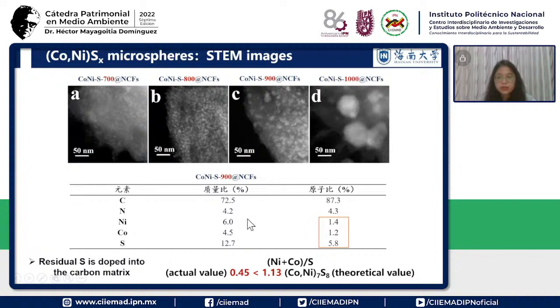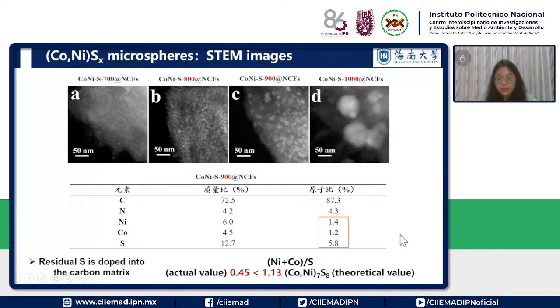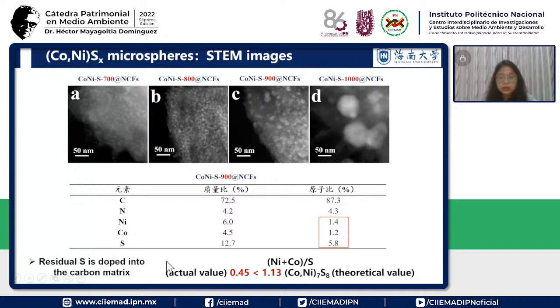The table shows the atomic ratios of different elements in sample 900, and we can find the sulfur here. The residual sulfur is doped into the carbon matrix, because for nickel plus cobalt to sulfur, the actual value is only 0.45, but the theoretical value should be 1.13. So we can say the residual sulfur is doped into the carbon.